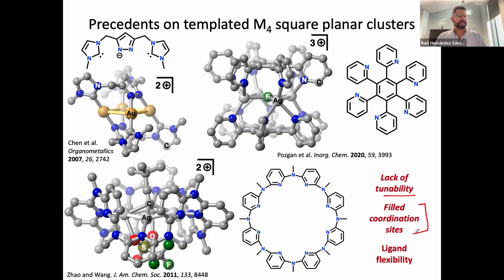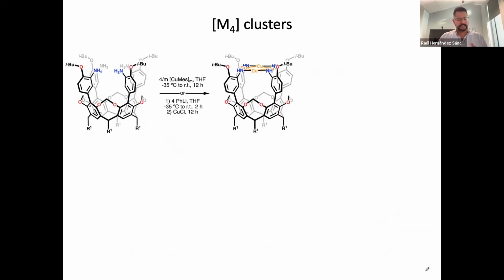You can also argue that the coordination sites are essentially filled, or there are no coordination sites because we have a d10 species in this case, or the ligand is too flexible, so that when subjected to stress, oxidative or reductive stress, it's likely going to fall apart. So what we ended up doing is synthesizing ligands that have a much more rigid structure that only presents the ligand donors into one particular region in space.